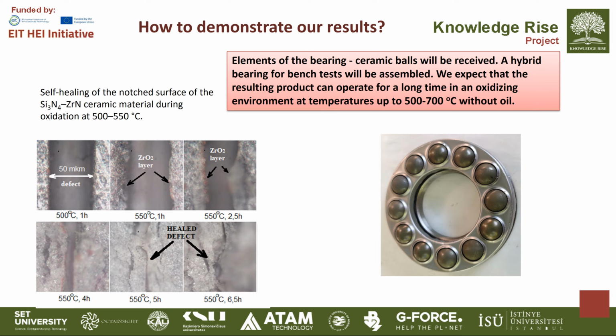Here you can see the mechanism of self-healing, the effect of self-healing for the ceramic based on silicon nitride. Here is a defect with a 50 micrometers width, and when we expose it at high temperatures around 500 or 550 degrees, the crack could be healed within 5 hours.